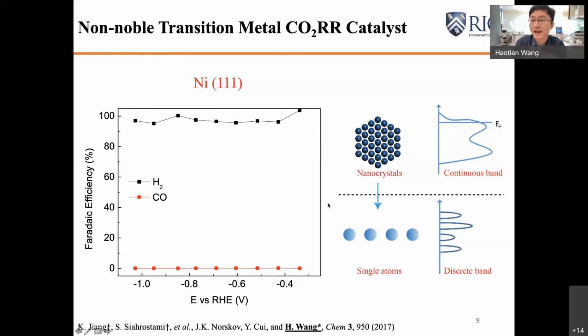But at that time, our idea was, what if we further shrink the size of nickel nanoparticles all the way down to single atom catalyst. The term single atom catalyst here is not like an isolated atom floating around in air. We are referring to separating the nickel metal atoms into isolated spots where we can use graphene defects to confine them in different locations. So there will not be any nickel-nickel direct interaction.